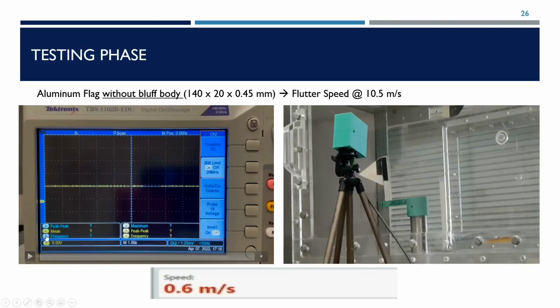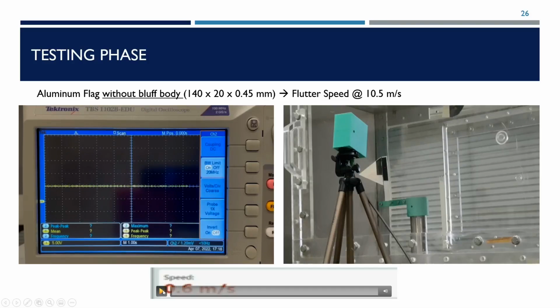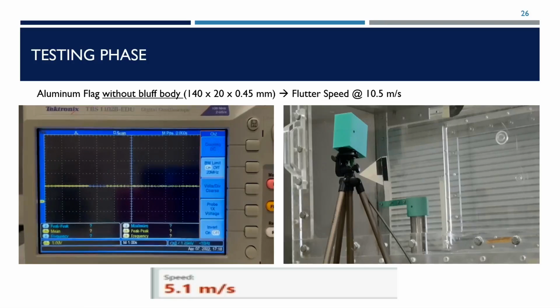Our second test uses an aluminum flag without a bluff body. The flag has the same dimensions as the galvanized steel. In this test, we concluded that the flutter velocity of this flag is about 10.5 meters per second.